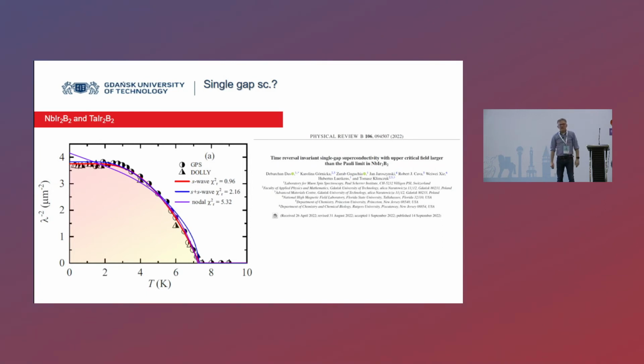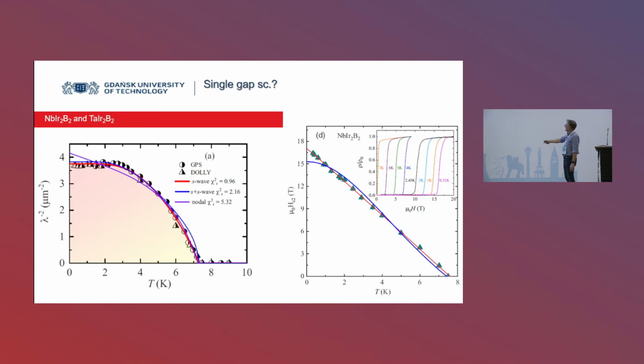It doesn't work. It doesn't work at all. So most likely, niobium iridium 2 B2 is a single gap superconductor, unfortunately. However, by the way, here is also the high magnetic field data collected in Tallahassee. So you can see that it's a linear behavior up to pretty much 16, 17 Tesla to the very low temperature, 0.32 Kelvin.